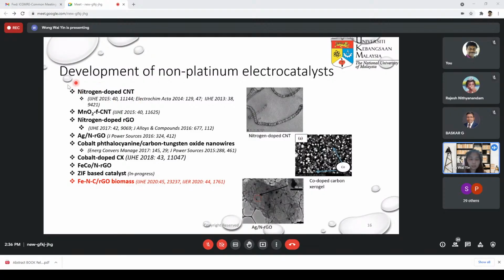In the beginning, we studied purely nitrogen doped carbon nanotube without metal. It's a metal-free catalyst. As mentioned, the results were not promising. And then slowly we moved on to the cobalt and iron-based, and also we looked into the metal organic framework catalyst, which is very promising at the moment. And also one thing to highlight is that we are also looking into the use of carbon nanostructure as a catalyst support material.